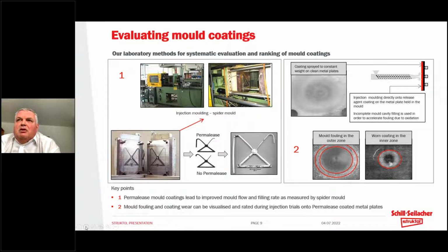Here again, we use an injection molding method, and we apply our mold release coating to a thin steel metal plate, which we apply then as an insert into the mold. So the coating is sprayed and cross-linked onto the metal plate, and the metal plate is fixed into the mold and held in place with magnets. We then inject directly onto this metal plate and force the compound to flow radially outwards from a central injection point. Absolutely not the ideal design for a mold, but it creates a very high impact area where we inject directly onto the surface of the mold and have a mold flow radially outwards, which causes then, of course, a very high wear, a very high abrasion behavior against the surface of the mold coating.